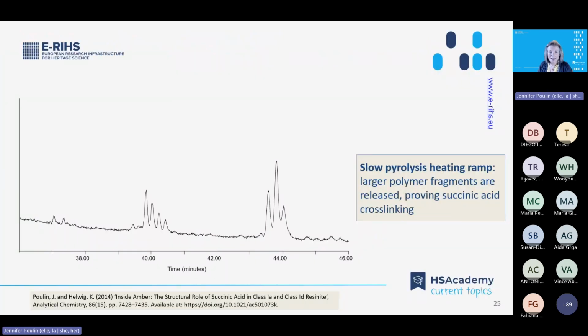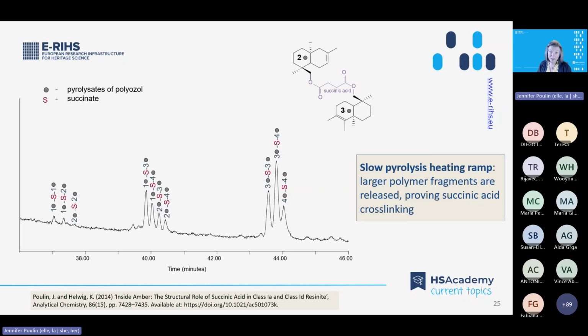These 10 peaks at the end of the run represent the 10 possible combinations of the 4 alcohol pyrolysates esterified with succinic acid. Using the slow pyrolysis, larger fragments of the polymer were remaining intact. These 10 peaks represent cross-linking of the amber polymer with succinic acid, and we can see clearly for the first time how the polymer was put together. Similar clusters of peaks occur with Baltic amber, which also contains succinic acid. So succinic acid cross-linking in Baltic amber had been hypothesized from the FTIR absorbance bands in 1972, but it wasn't proven until these experiments at the CCI with slow pyrolysis.